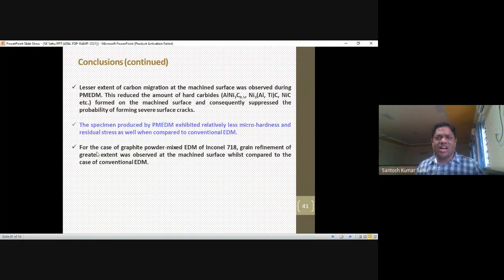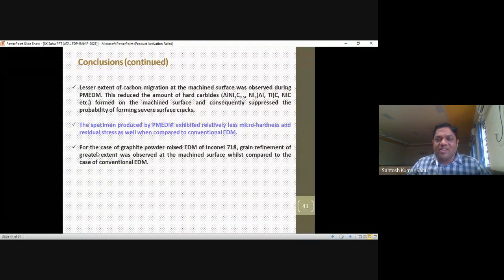Also you have to know that cracking is a major limitation in any manufacturing area, and the specimen produced by powder mix EDM exhibits relatively less micro hardness and residual stress as compared to conventional EDM. So finally, for graphite powder mix EDM of Inconel 718, grain refinement to a greater extent was observed at the machined surface compared to conventional EDM. So that is all I have to conclude about my first part.